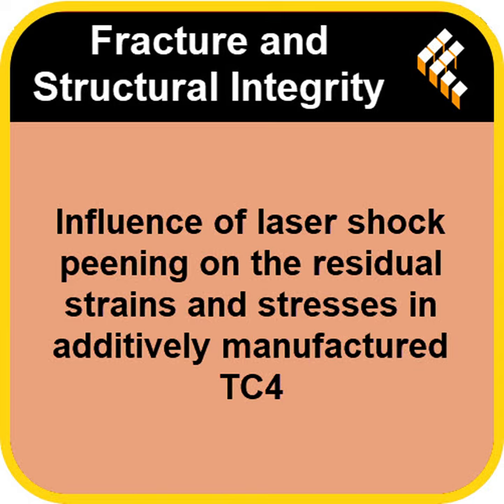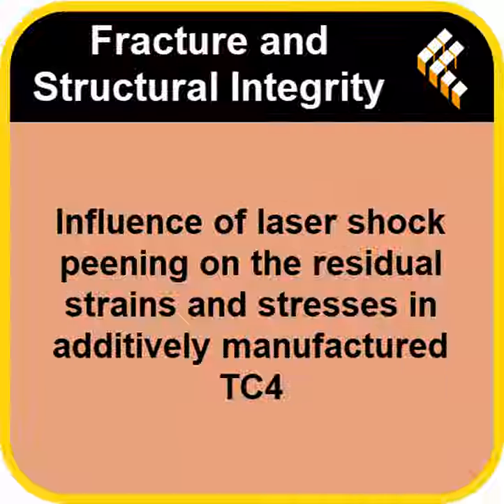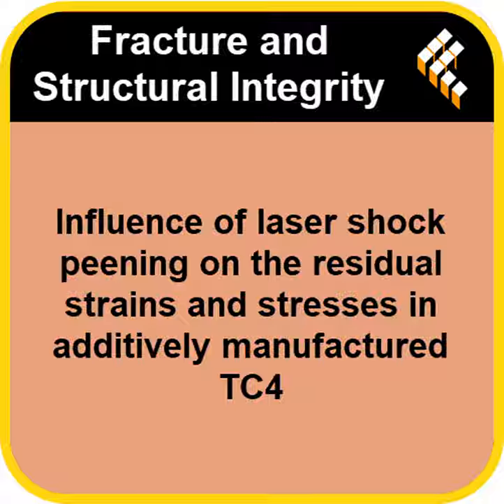So the model lets you see the internal stress in places measurement can't reach. Exactly. You can simulate the LSP treatment on a complex CAD model and predict the resulting stress profile with high confidence. That's the engineering breakthrough. Okay, let's wrap this up. We started with this inherent problem in metal AM, those bad tensile stresses. Yep, the downside of that rapid heating and cooling. But we found laser shock peening is a really effective tool to flip those into beneficial compressive stresses. Improving fatigue life, likely closing up some internal porosity too, especially in critical materials like TC4 titanium.